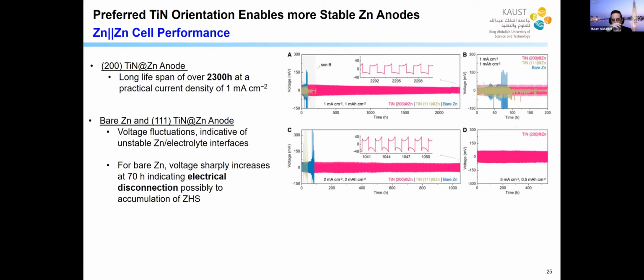So the first experiment we do is a symmetric cell performance to look at the cycling stability of the stripping and deposition process. So here you see three samples. You see the pink, which is the 200 oriented titanium nitride. You see the blue, which is 111 oriented titanium nitride, and you see the golden color, which is the bare zinc without the titanium nitride. Obviously, you can see that we can go to 2,300 hours of cycling.